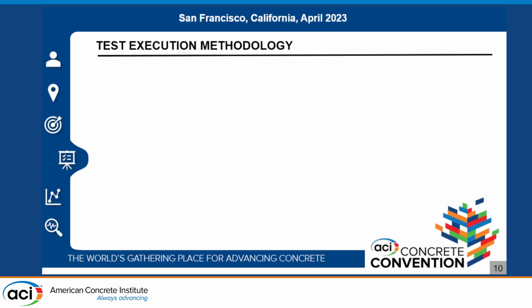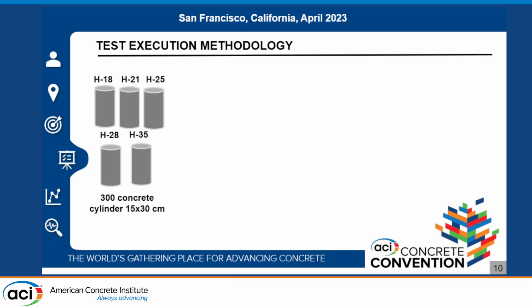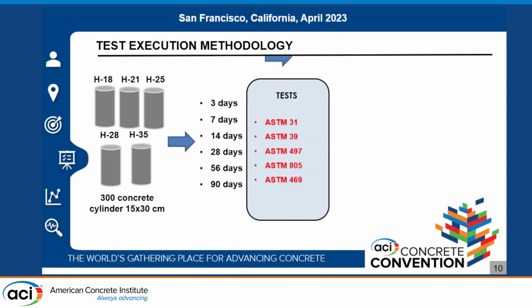The test execution methodology consists first of all in the elaboration of 300 concrete cylinders with dimensions of 15 by 30 centimeters, of concrete mixtures with design resistance from 18 to 35 megapascals reached at 28 days. They were tested from 3 to 90 days. The tests applied were ASTM C31, C39, C597, C805, and C469.